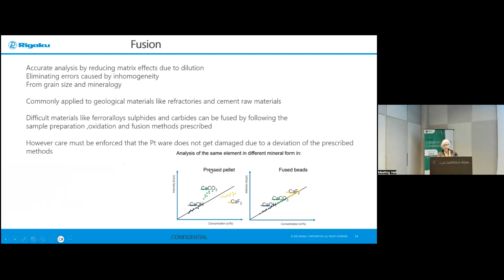But here you can see an example of a calibration where we have pressed powder. The problem with pressed powder is the matrix. If you look at calcium, it can exist as calcium oxide, calcium carbonate, calcium fluoride. So they are all calcium. We want to measure calcium, but unfortunately they exist in different matrices. That means if you measure a sample by XRF with pressed powder, we will have different calibration curves.